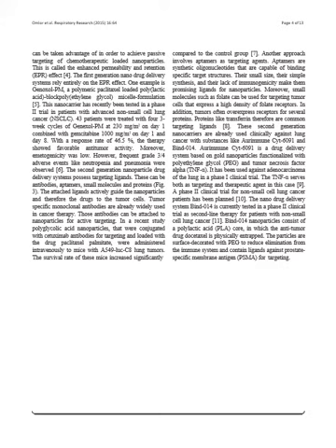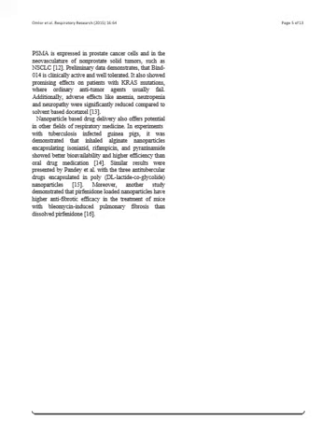BIND 014 nanoparticles consist of a polylactic acid core in which the anti-tumor drug docetaxel is physically entrapped. The particles are surface decorated with PEG to reduce elimination by the immune system and contain ligands against prostate-specific membrane antigen for targeting.